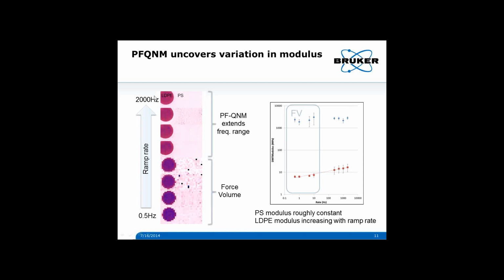But if you look at the LDPE part of this sample, this circle, it's actually getting to be a darker purple as we go down to lower ramp rates. And so basically you can look at the average of these areas and put it into a plot, and you see that our force volume and peak force tapping data for polystyrene is all roughly about the same value. Whereas with LDPE, it's actually increasing as I go to higher ramp rates. That's similar to what the polypropylene suggested it would do. And actually, this is a log-log plot, so this is increasing by about a factor of 3 over that frequency range.